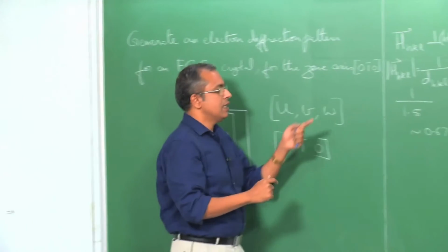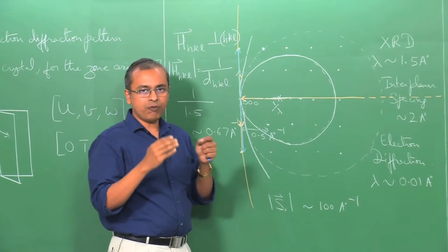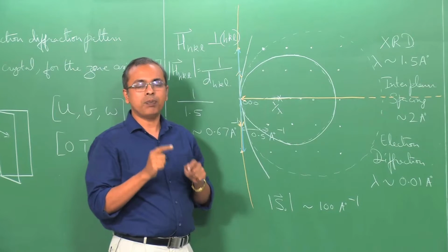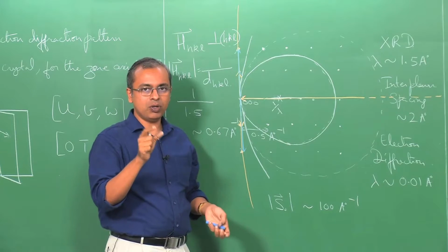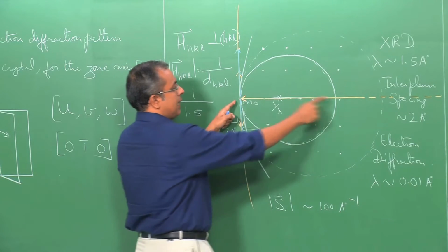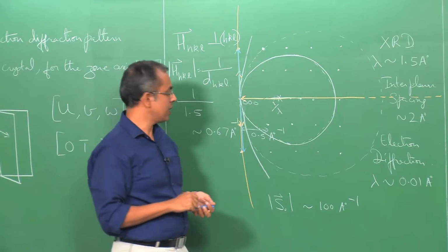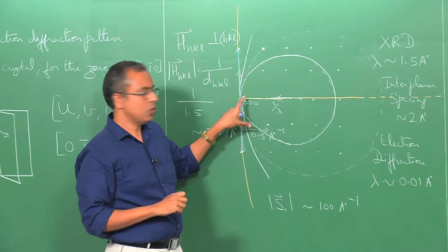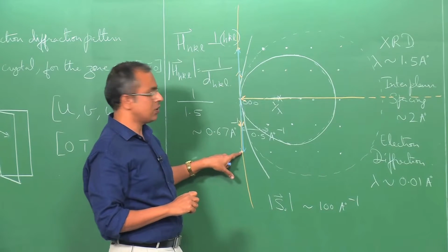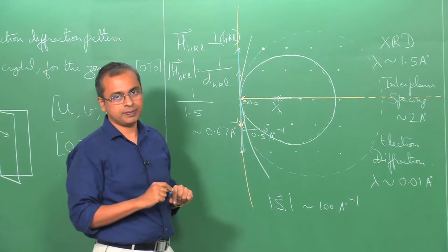So, therefore, when you take electron diffraction, the pattern of points that you see represent points of a zone. They are all vectors which belong to that zone axis, and the beam direction coincides with that zone axis. So, that is the important point that we wish to note. Okay. That is the peculiar thing about electron diffraction, and how it shows you the spots that you see there, which are all spots corresponding to the same zone, right.